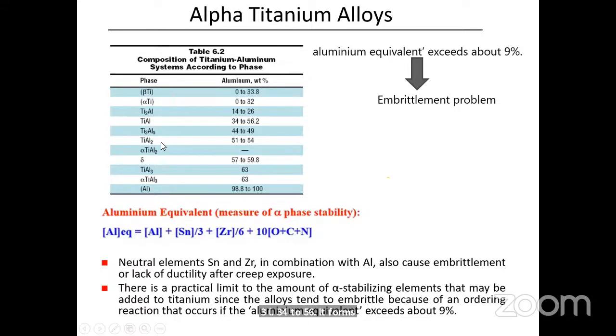So generally, the stability of the alpha phase can be defined by using this equation called aluminum equivalent: aluminum plus tin by 3, zirconium by 6, and 10 times the oxygen. When you are adding a small amount of oxygen, carbon or nitrogen, because it is multiplied with 10, the aluminum equivalent will increase. If it crosses greater than 9%, then it's a problem, embrittlement occurs. That's why you need to keep the aluminum equivalent less than 9%, so that you can use it for commercial applications.